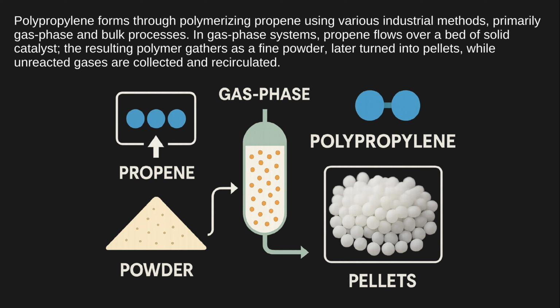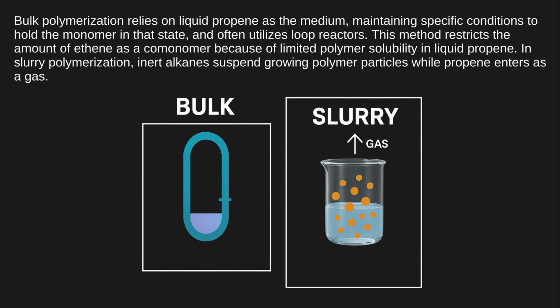Polypropylene forms through polymerizing propene using various industrial methods, primarily gas phase and bulk processes. In gas phase systems, propene flows over a bed of solid catalyst. The resulting polymer gathers as a fine powder, later turned into pellets while unreacted gases are collected and recirculated. Bulk polymerization relies on liquid propene as the medium, maintaining specific conditions to hold the monomer in that state, and often utilizes loop reactors. This method restricts the amount of ethene as a comonomer because of limited polymer solubility in liquid propene. In slurry polymerization, inert alkanes suspend growing polymer particles while propene enters as a gas.